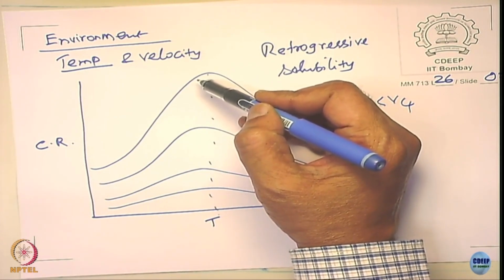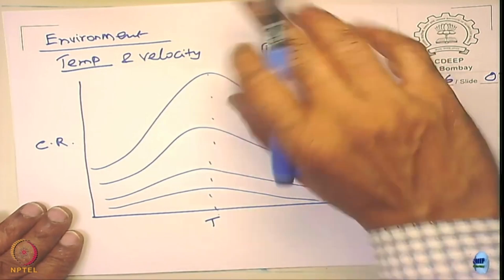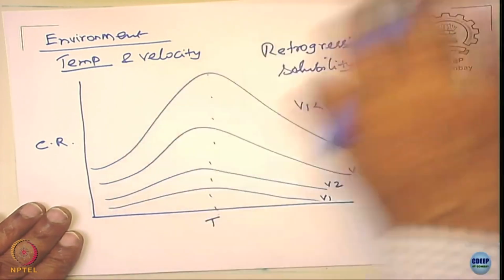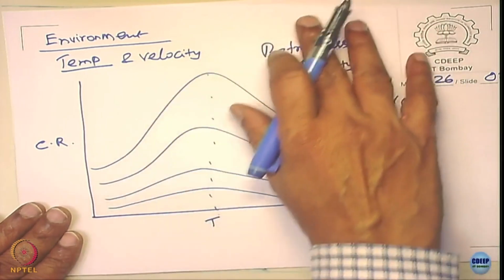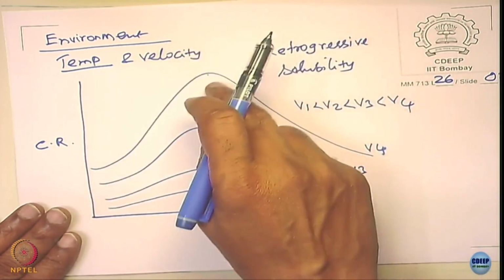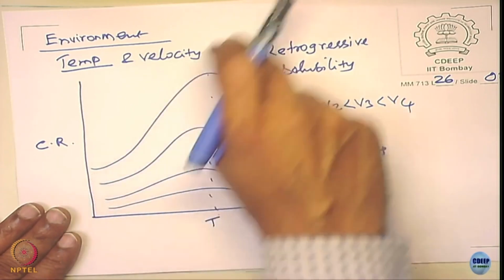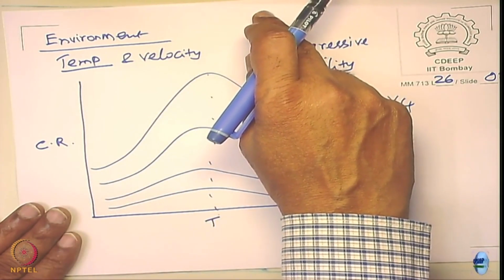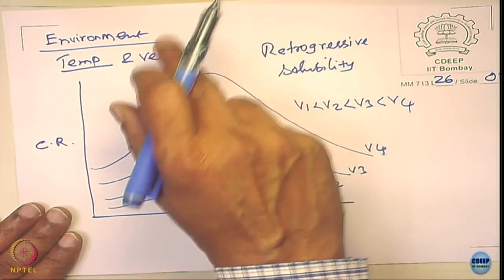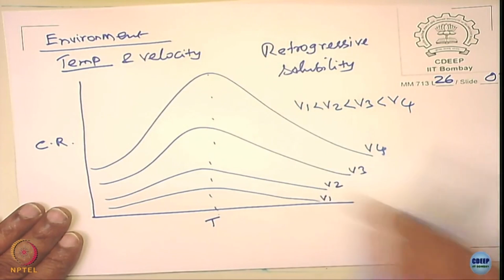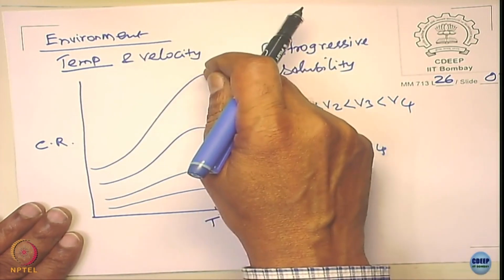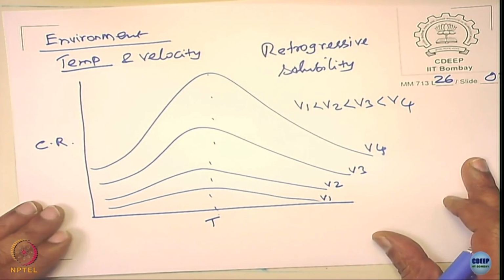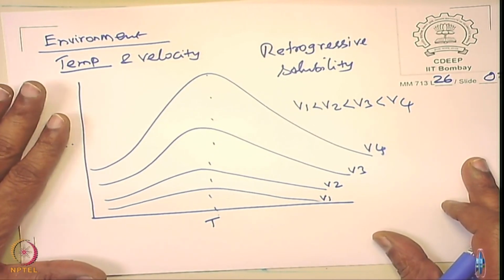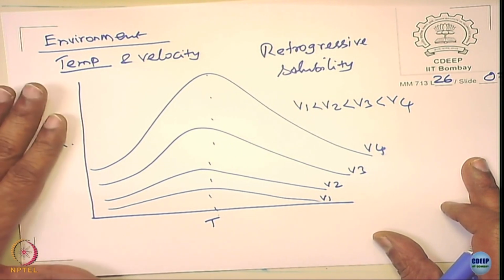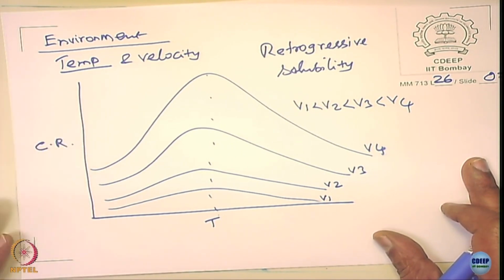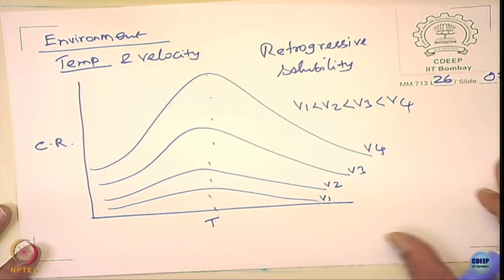Assume that there is no film on the surface. The rise in temperature will only lead to an increase in the corrosion rate, am I right? Assume that no film is formed, and if you raise only the temperature, the corrosion rate only will increase with temperature. But there are two factors: the rise in temperature increases the corrosion rate, but it also increases the scale forming tendency. So the corrosion rate starts falling like this. You have an optimum value here wherein the corrosion rate is highest and then it starts falling. This is typical of what you find in thermal power plants, operating for the utilities actually.